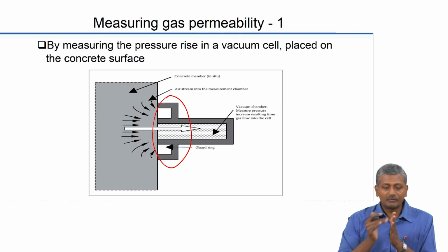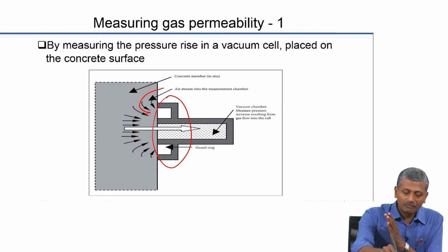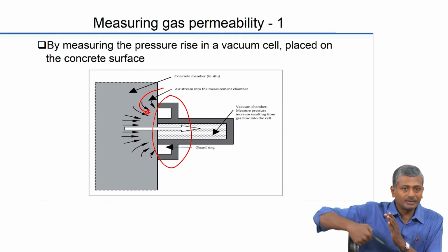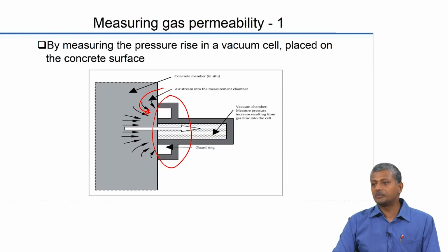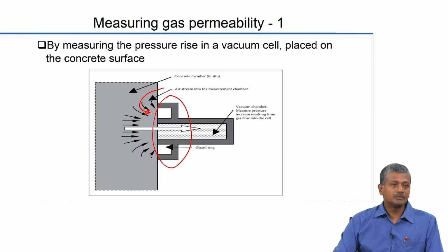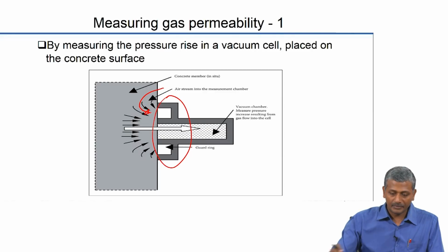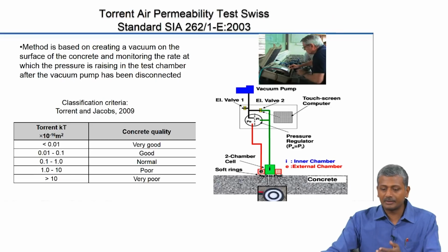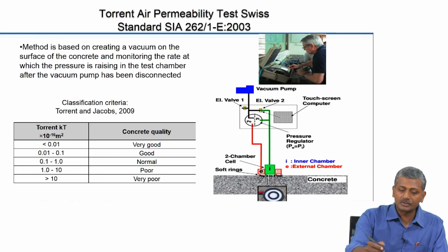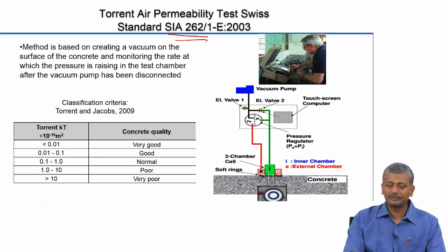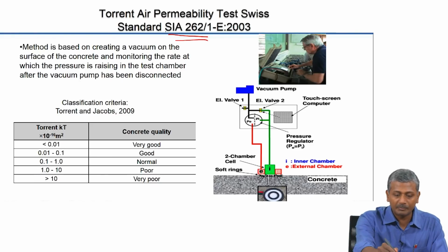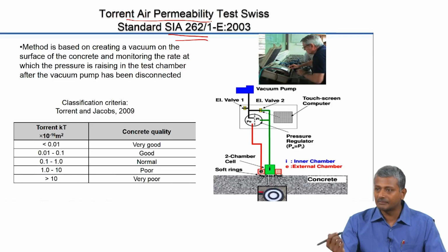So, the air which is flowing from the sides will tend to go through the porosity of concrete and disturb the vacuum inside the cell, and that can be gauged as the permeability coefficient of the concrete. Okay. So, that is what is happening in this case, and this test has been standardized in Switzerland. It is a Swiss standard test, and it is also available with an instrument called Torrent Air Permeability Tester. Okay. And we have this instrument in our lab.